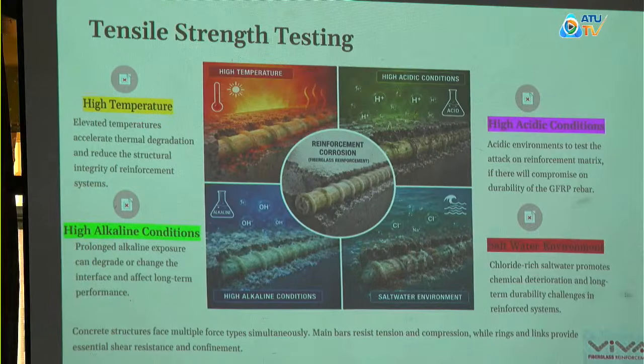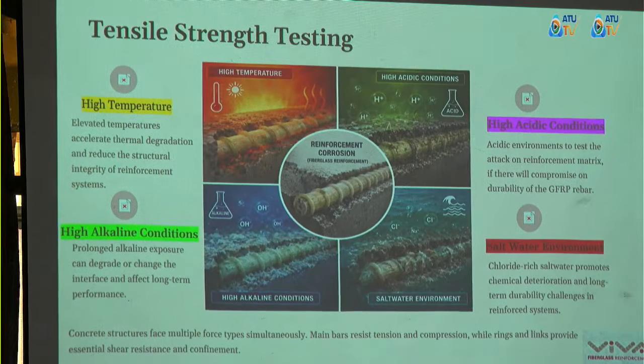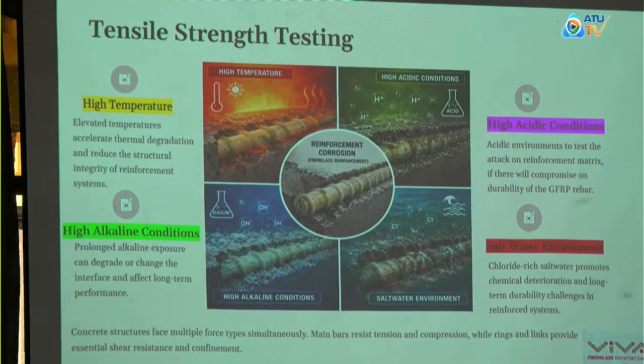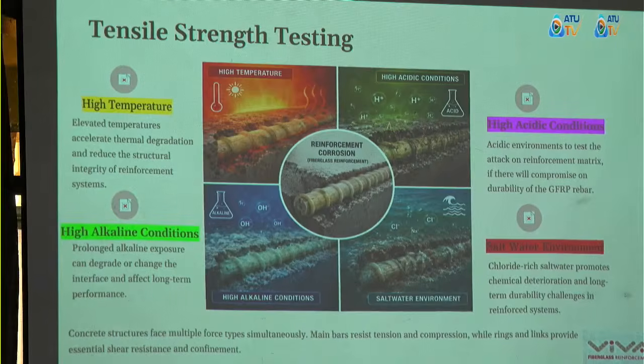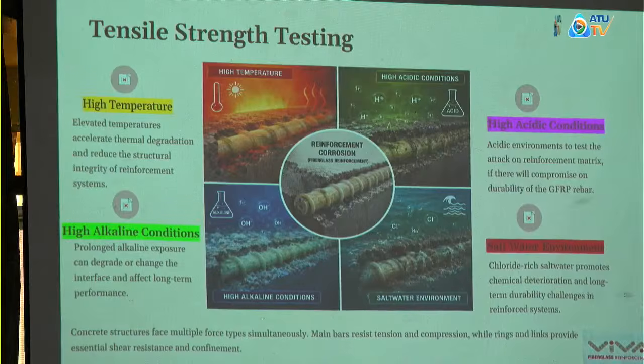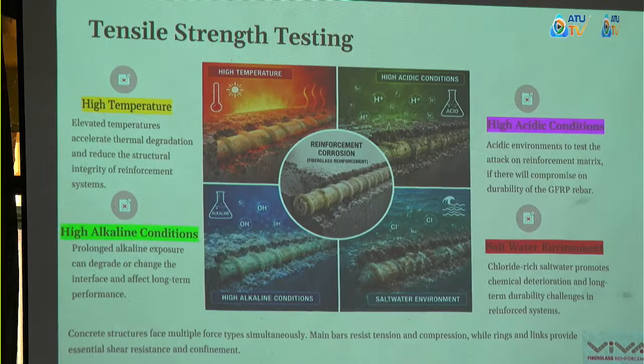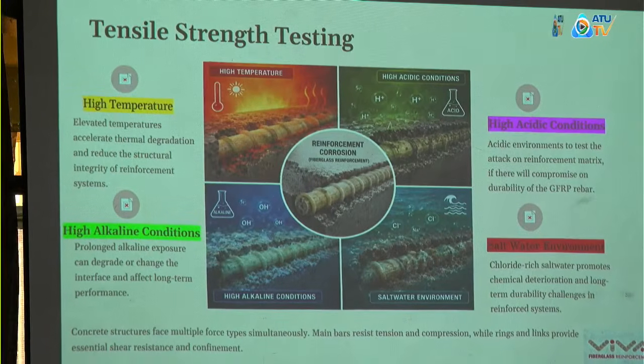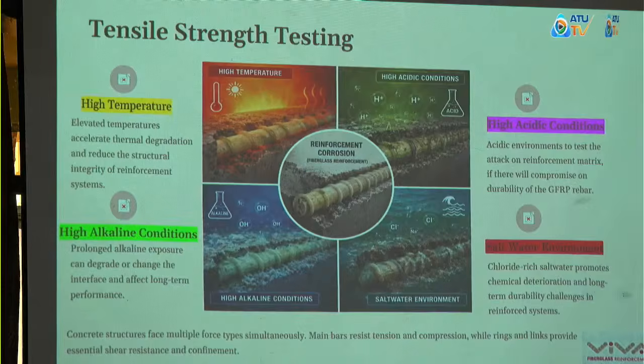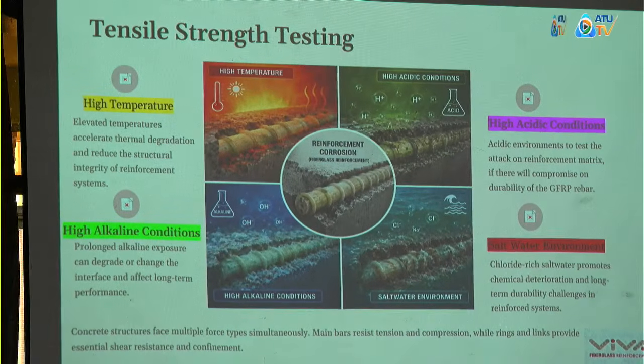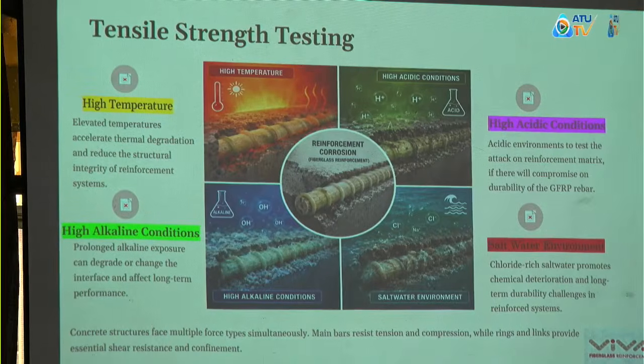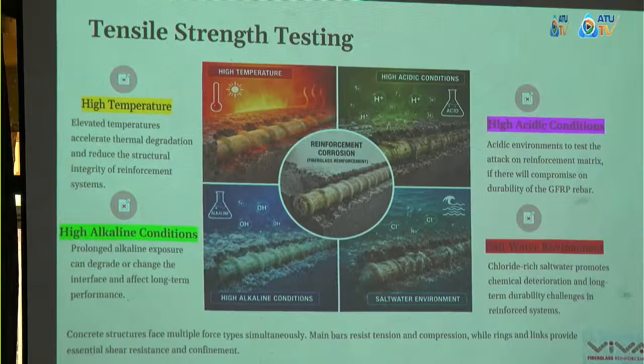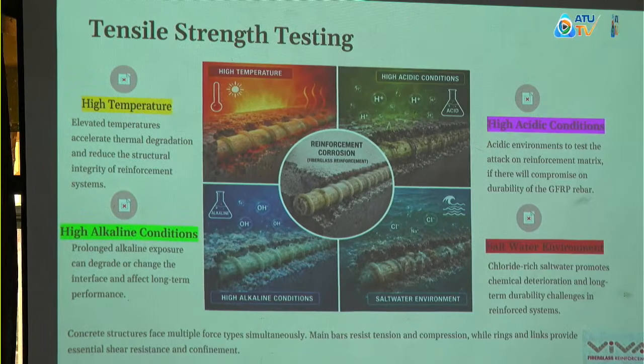Upon all these subjections of the reinforcement to harsh environmental conditions, I can attest that there were barely any changes. The change in the tensile strength was basically between 3 to 5%, and all the samples achieved a minimum of 1,150 megapascals, which was not significant because the material is not corroded by the acidic condition, is not affected by the temperatures of 230 and 240 degrees, it's not affected by the high alkaline conditions, and also not affected by the saltwater environment like the steel reinforcement that we are using.